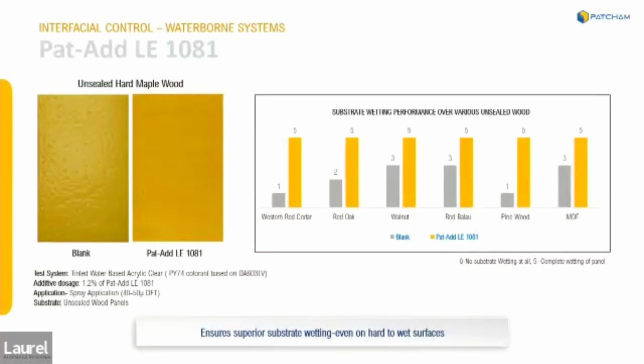In our transition from solvent-borne toward less solvent because of the impact of solvent on the environment, some companies have switched their interest to waterborne technology. Waterborne is a very interesting technology. For the formulator, it's a big challenge, because when you make waterborne coatings, sometime during the transition of that coating from a waterborne coating to a solid film, it's no longer a waterborne coating, and everything we use to stabilize the particles that we put into this coating, the emulsion particles, the pigment particles, the fillers, and all those other things, they're no longer compatible and stable in the system because all the water's evaporated, it's gone.